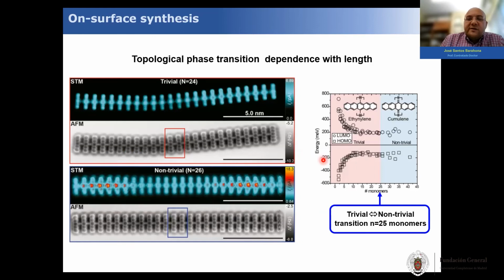Well, by plotting the different sizes of chains, we can find that the limit for the non-trivial range lies at n equals 25 monomers. So once we transition from 24 to 26, we are starting to be in the range of the non-trivial structure polymers. I think this is probably the first time that this sort of experiment is being carried out, and these are probably the first non-trivial polymers ever found on a surface.